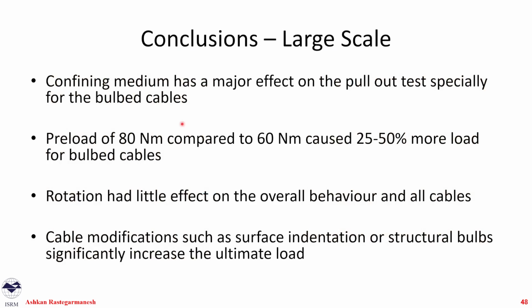Okay, a couple of take-home notes or conclusions to talk about. So confining medium has a major effect. We already saw that between the large and small scale tests and for the preload torques that we put on the bolts. The preload of 80 compared to 60 Newton meter had up to 50% effect on our test. Rotation had overall little effect for the tests that we did. Obviously, we need to study it more.